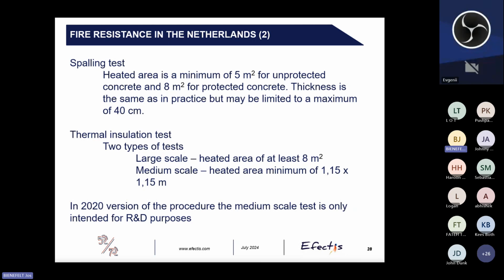The thermal insulation test is actually divided again in two different tests, a large scale and a medium scale test. The large scale test has a heated area of at least 8 square meters, and the medium scale test has a heated area of a minimum of 1.15 times 1.15 meters. And in the 2020 version of the procedure, the medium scale tests may only be used for R&D purposes.